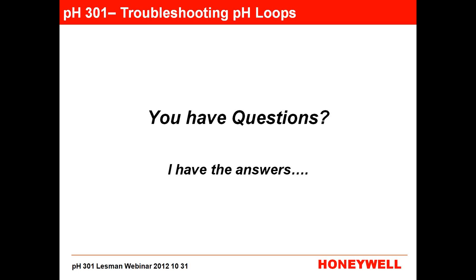All right, another question we have is from Craig. Do you know if USP states anything about not using temperature compensation? And is it a better idea to use temperature compensation? Okay. In general, when you measure pH, you must use temperature compensation. If you don't have temperature compensation, I should have put that graph in there. I debated it in my presentation. If you don't use temperature compensation and you're away from 25 degrees C, you're going to have an error in your measurement in general. This is the general answer, and then I'll give you an answer on specific USP.